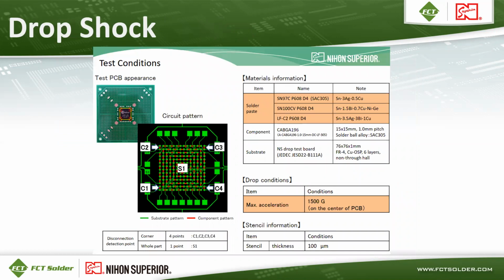Here's data and information on a drop shock test that was performed on those three alloys. The solder pastes that were used had SAC 305 at the top, then SN100CV in the center, and LFC2 at the bottom of that list. The component that was used was a BGA 196, and this was done with an acceleration of 1500 G. You can see the diagram of the BGA on the left and the circuit pattern that was used. The corners are labeled C1, C2, C3, and C4 for reference.